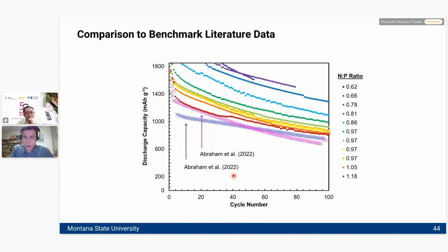Our data compare favorably with other data in the literature. It depends on where you look, obviously, but as far as pure silicon anodes go in the presence of a liquid electrolyte, these are some of the highest capacities over the first 100 cycles that we've ever seen. And so we're pretty proud of the performance we're able to get out of these particle size mixed electrodes.